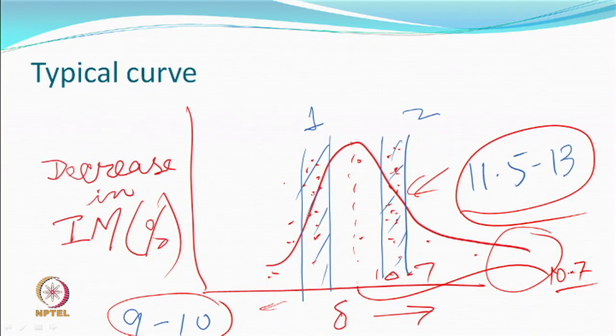So, the solvents which are very far off are not good obviously, but exactly in the center also they are not. One or two solvents were not really working because they were happy with neither the aliphatic part of the polyester nor the aromatic part of the polyester, and therefore, it is segmental stuff.